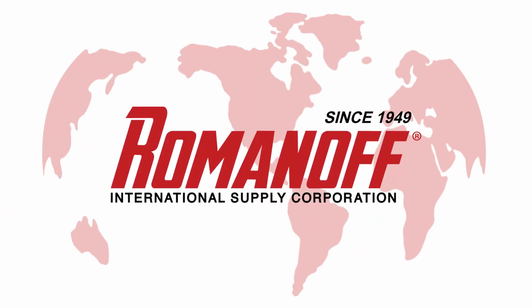Gas porosity in castings results from gases being absorbed into the metal during the hot molten state and remaining when the casting becomes chilled and solidifies. To prevent gas porosity, one must first prevent gases from being introduced into the molten metal by melting in a controlled atmosphere, which means vacuum and then argon gas. In the event some gases are introduced into molten metal, their escape before the casting solidifies should be made as easily as possible. Let's look at the introduction of the gases.